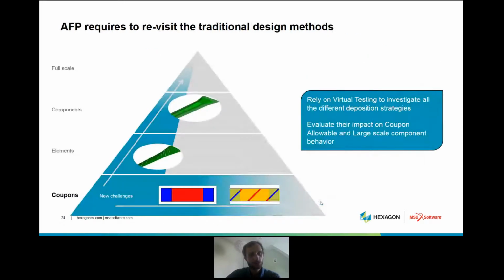And this means that once we start introducing automatic fiber placement in engineering workflows, we need to revisit the traditional design methods, because with these automated manufacturing techniques we have defects that are introduced and that need to be characterized. And hopefully, since those defects can also be quite well controlled, we need to understand what the right trade-offs are in terms of how wide the gap can be, and how it should be positioned compared to a hole in a part. This means that new approaches are needed across the scales, starting from the coupon level to the elements and then to the final components, which are all impacted by the defects and gaps.